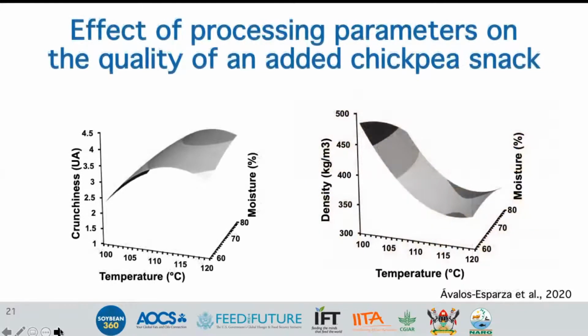The addition of alternative ingredients with high fiber or protein content significantly affects the texture and density of the product. The crunchiness is a characteristic parameter of the texture of third-generation snacks. The best texture parameters were obtained in the snacks with the highest expansion index, which was reflected in a higher crispness as well as a lower density, which indicates a less hard snack. The samples processed at 120 degrees and 80% moisture were those with the best expansion and crispness index.